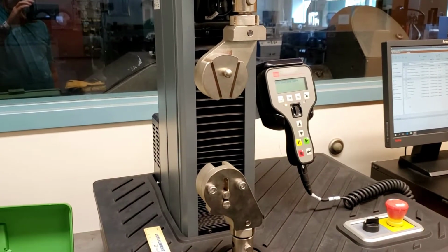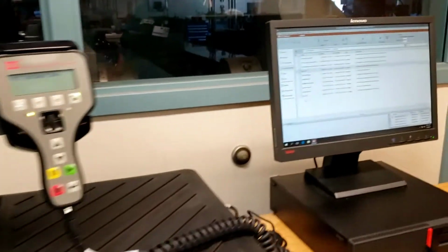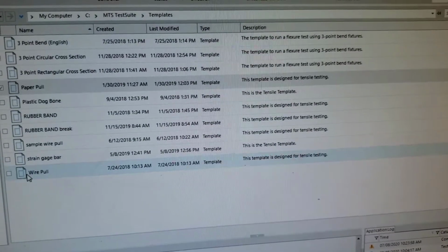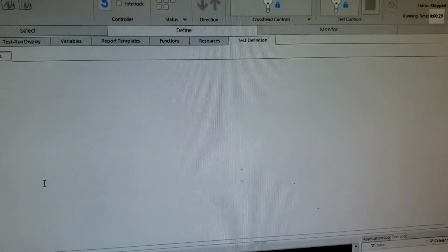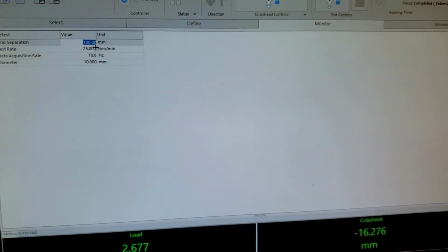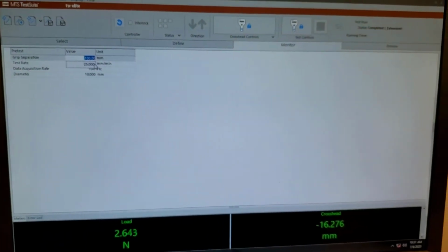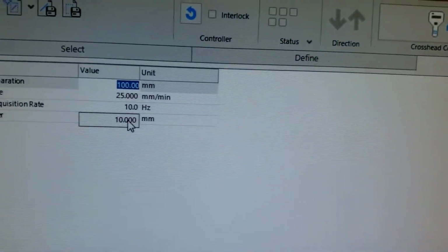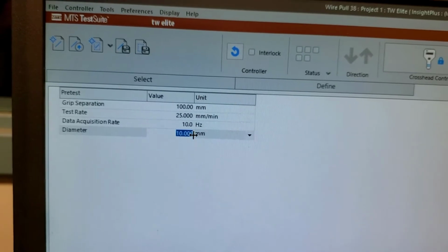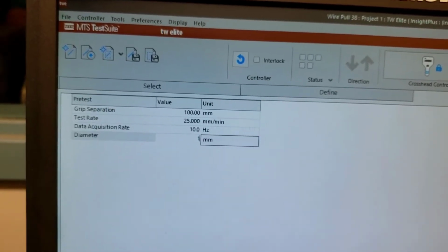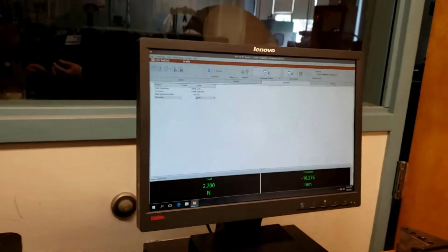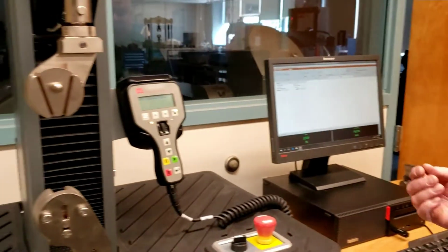And my test sample on the computer is I want to use the wire pull, and it's the one on the bottom. And there it is, and we'll bring that up. And you'll see grip separation 100 millimeters, my test rate, and my initial wire diameter, which is not 10 millimeters, it is 1. Okay, so what I'm going to do now is set the wire up, and then we'll come back and actually run the experiment.